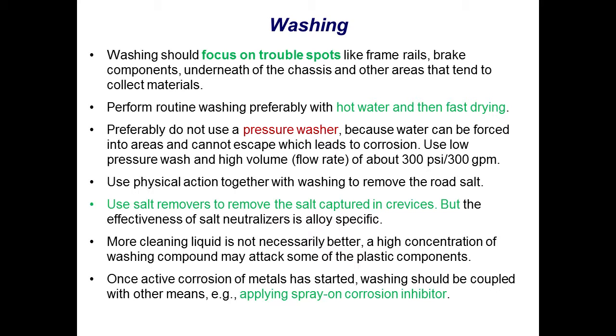Washing should focus on trouble areas. That's kind of intuitive. And one thing we learned from the survey and also from our own lab testing is that usually after washing, you better dry it fast, because the corrosion really kicks in at the humid stage. Once the humidity drops to, say, below 30%, corrosion basically stops. Okay. So pressure washing, it seems like pressure washing is not best practice. Need to do it a different way. Use salt removers and so on.